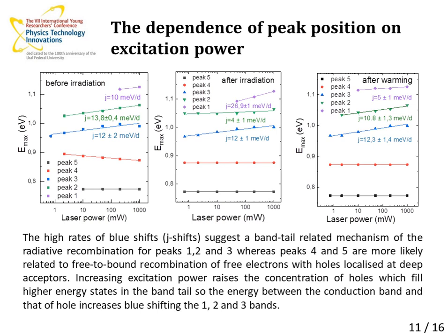Increasing excitation power raises the concentration of holes, which fill higher energy states in the band tail, so the energy between the conduction band and that of the hole increases, blue shifting the first, second, and third bands.